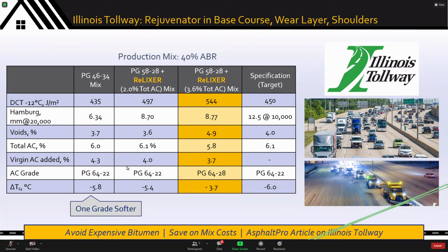What you can also see is the exceptional aging resistance. Delta TC is a measure of aging resistance. I'll talk about it a little bit more, but also the dosage efficiency. Here you can see the reduction in the virgin bitumen added into the mix. And again, that's what helped provide, while maintaining properties, a measure of cost reduction from their baseline mix.